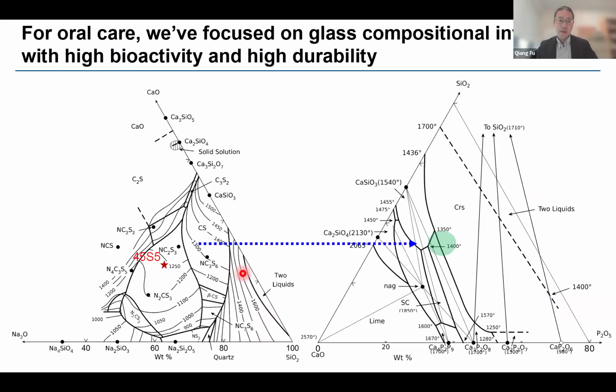So in this case, we switched the system in bioglass from this sodium calcium silicate ternary diagram. We looked into this calcium phosphate silicate phase diagram. We identified an area around the eutectic in this phase diagram, and we invented a few compositions that look very promising when we compare with 45S5 glasses. Just want to show some data we have collected so far.